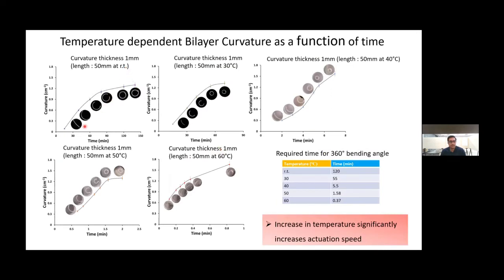We have observed the temperature-dependent bilayer curvature formation, and we found that with increasing temperature, the actuation speed also increases. You can see in this condition, where the thickness of the structure is 1 millimeter and the length is 50 millimeters, at room temperature it takes 120 minutes to form this coil, 360 degree structure. But if we increase the temperature from room temperature to 60 degrees Celsius, it takes only 0.37 minutes.